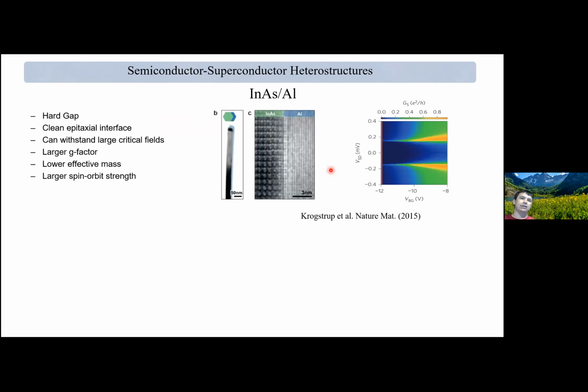So these initial papers actually inspired a lot of experimental activity, both in measurements and detection, but also in material science. Material scientists took it seriously that the interface needs to be improved, and they came up with different ways to clean and make these interfaces epitaxial. This is one of the early papers by Peter Krogstrup, who showed that indium arsenide wire and aluminum have a very good interface, and if you grow it epitaxially, the density of states looks like BCS and looks very clean.